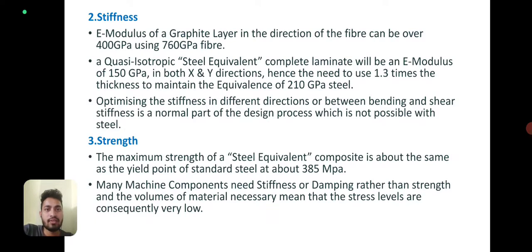Second one is stiffness. E modulus of a graphite layer in the direction of the fiber can be over 400 gigapascal using 760 gigapascal fiber. A quasi-isotropic steel equivalent composite laminate will have an E modulus of 150 gigapascal in both x and y directions. Hence, the need to use 1.3 times the thickness to maintain the equivalency of 210 gigapascal steel. Optimizing the stiffness in different directions or between bending and shear stiffness is a normal part of the design process, which is not possible with steel.